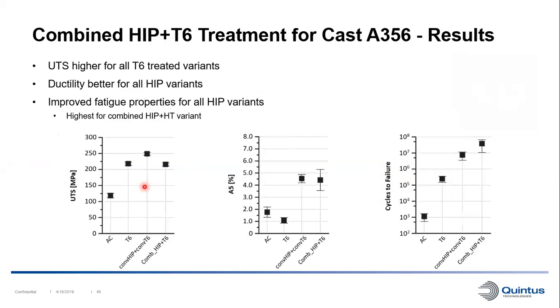And here we can see the UTS and elongation. We get better UTS as expected for the heat-treated variants, and the ductility is significantly higher for the two variants that are HIP'd compared to the as-cast material and the as-heat-treated material.